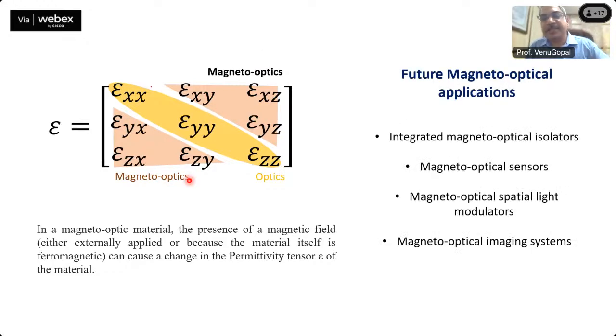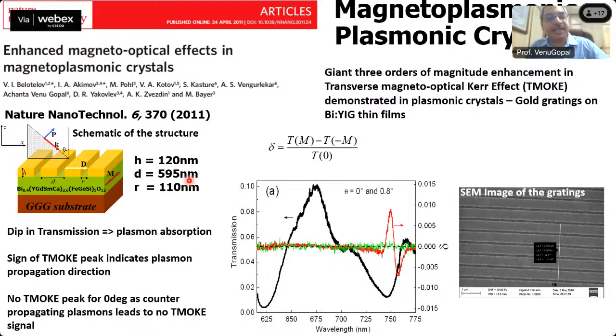Right. So it has large applications. I'll show you three different studies where the magneto-optical properties of the material got changed because of this plasmon excitation, because of the strong local field, which is enhanced due to the plasmon excitation. So when light is incident, you get this strong plasmon excitation of the local field, which leads to enhancement in your magneto-optical response. So here we showed 3 orders of magnitude enhancement in the Kerr signal just by patterning the top gold pattern. This is a grating structure in this case.